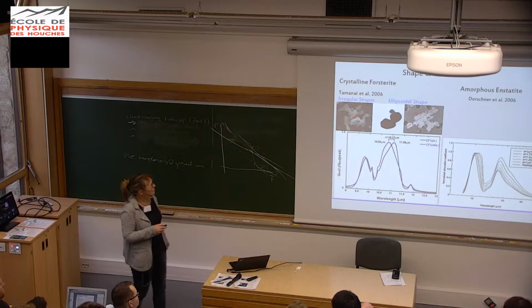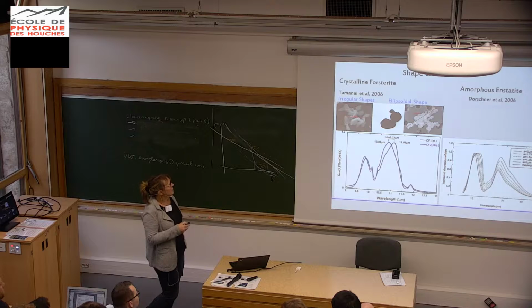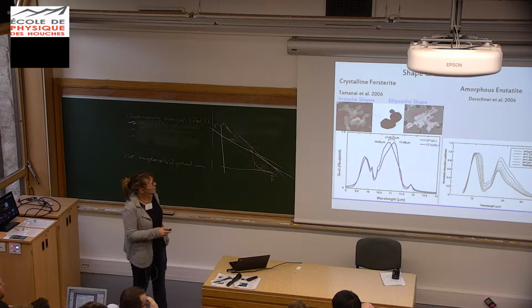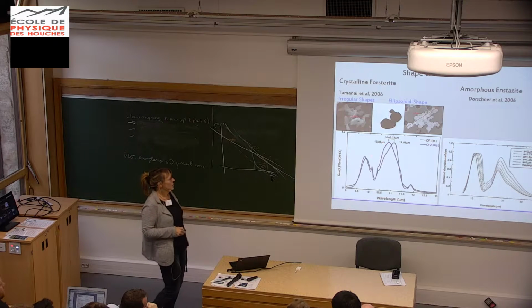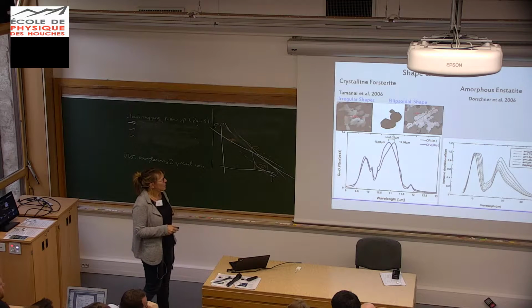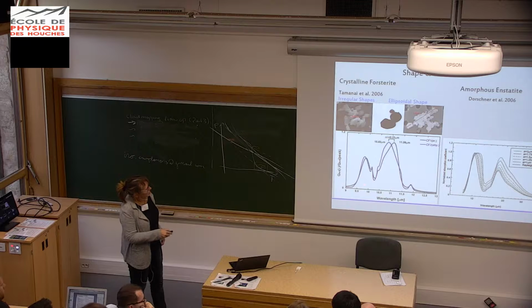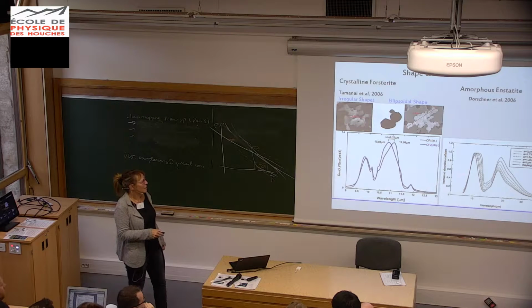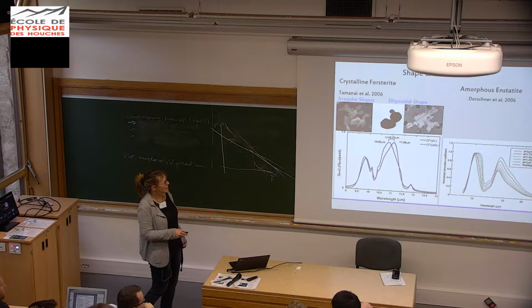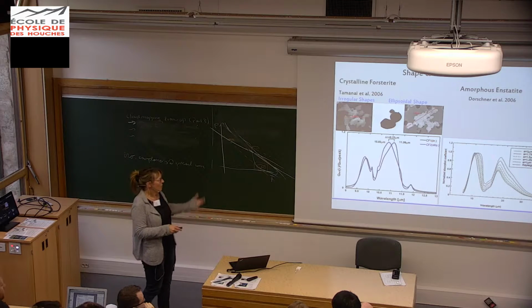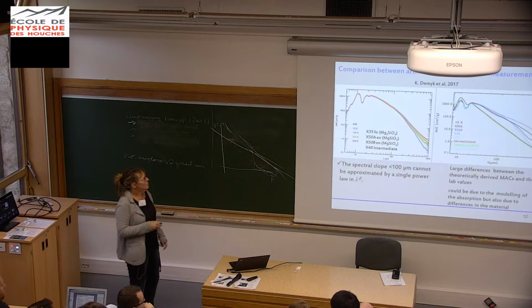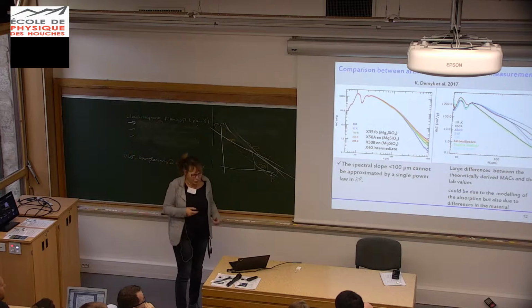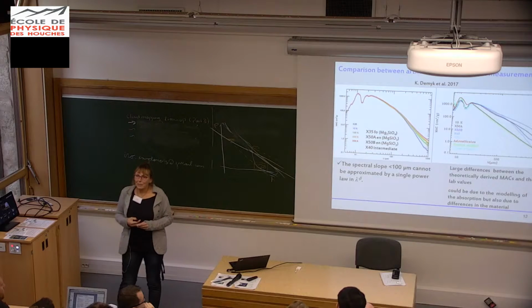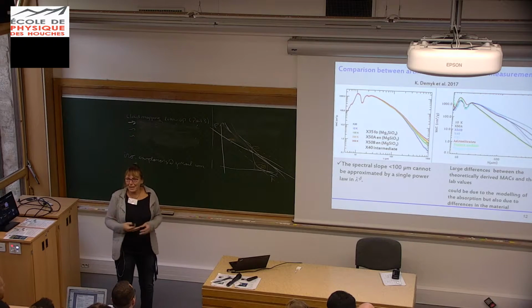Here I can show you something studied by Tamanai et al. 2006. She tried to measure the influence of irregular and ellipsoidal shapes on the profiles of crystalline silicates, and you see there are changes due to the shapes of the material, and of course the sizes matter. If you increase the size of the grains from the Rayleigh case to larger particles, you also broaden and shift. These are effects which are very important to know if you want to interpret your spectra concerning the type of silicate you have produced.